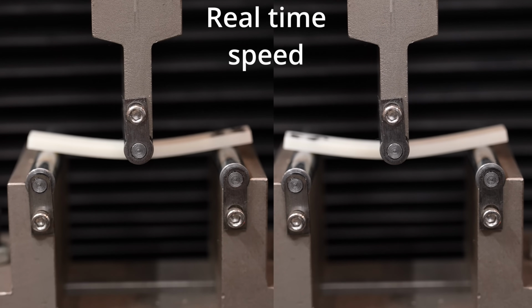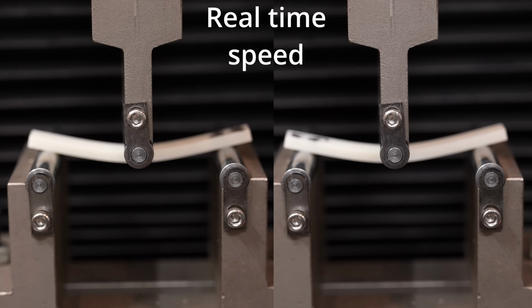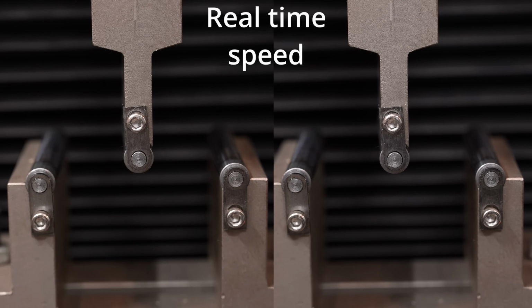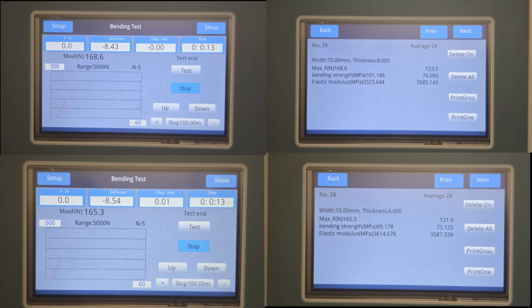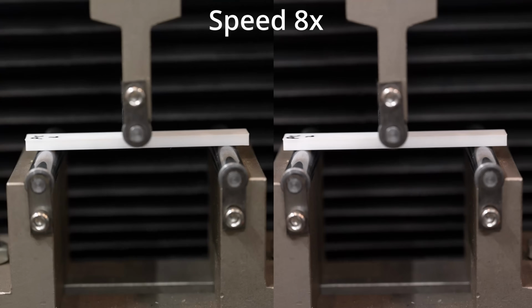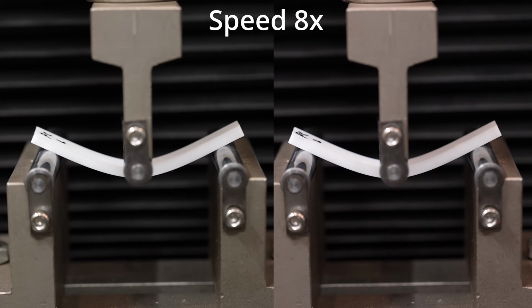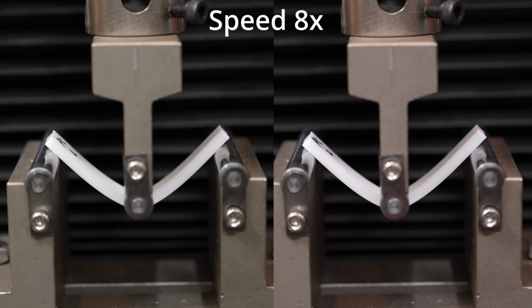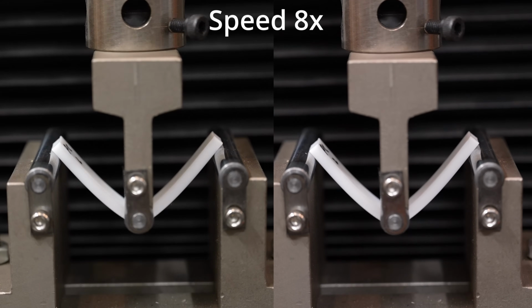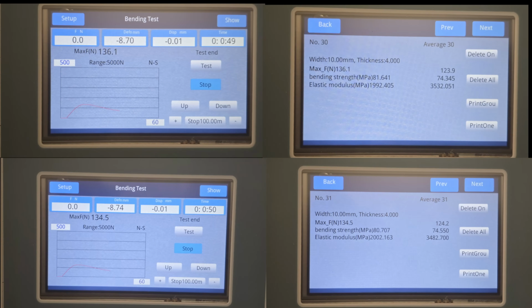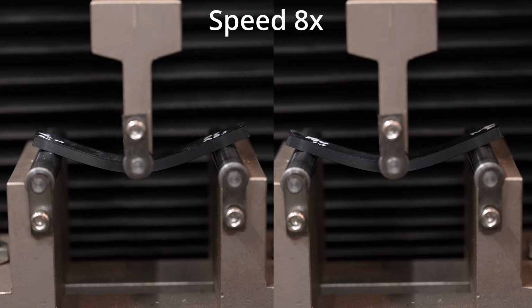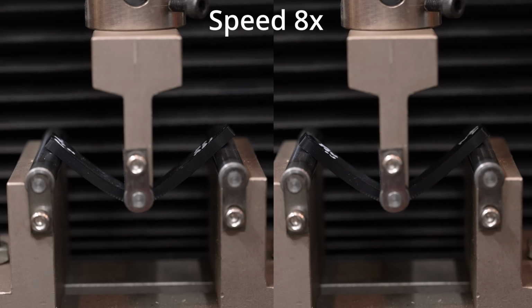3-point bending test. Distance between supports is 64 mm based on ISO 178. Starting with ABS-GF, real-time speed, because it breaks very suddenly. This is polycarbonate sped up 8 times. No break. And here you can see the graph and also the bending strength and elastic modulus. And very similar behavior with the PC ABS. No complete break.